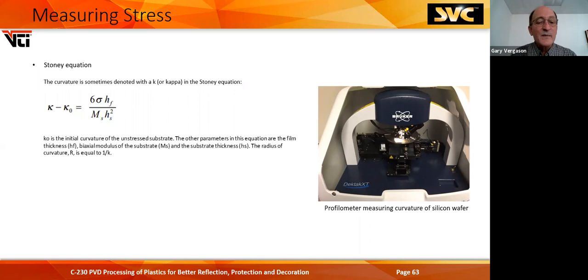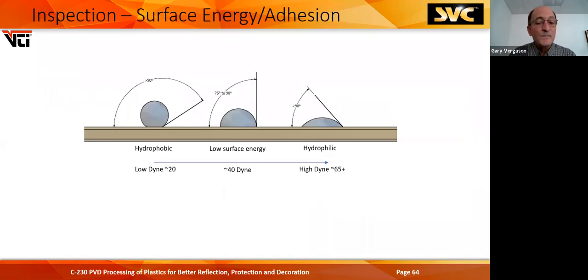Stoney equations can be used for measuring the curvature. We use a Dektak profilometer for that. We look at surface energy. We need to measure that. On the left, you've got your hydrophobic, very low dyne surface energy. We're usually around 40-ish dyne for most of the coatings that we do. And it can be as high as 65 dyne for your hydrophilic coatings. So we're looking at the contact angle measurement, and that's what this slide projects.